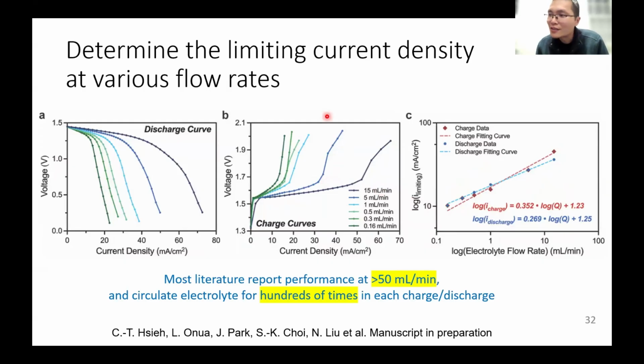So this is some results. We're organizing these results and try to submit the paper soon. But I will give you a little bit of taste of the results. So what we did is to do a polarization experiment to figure out what's the current you can apply at different flow rate, right? We reduce flow rate from 50 to 15, and then to even lower than that, down to even 0.16 milliliter per minute.